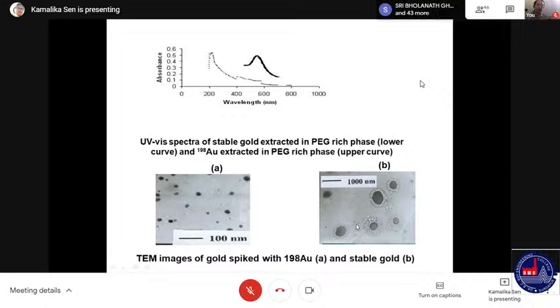A similar solution prepared with stable gold solution gave very large particles. You can see the scale, and this is not a particle actually. This is a patch, and this does not form any kind of nanoparticle.